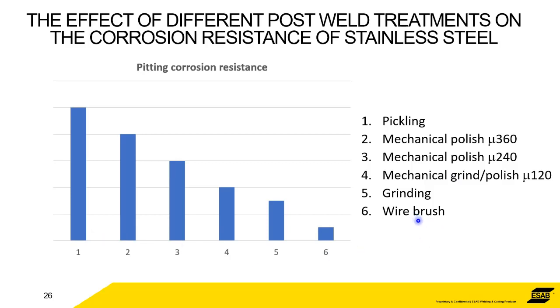Number 6, we've got the wire brush. So it doesn't really matter what the numbers are. We're just trying to illustrate that pickling is 10 times better than using a wire brush. Grinding is 3 or 4 times better than a wire brush, because you're sure to get rid of both the heat affected zone, the heat tint, and the chrome depleted zone underneath. You're sure to get rid of that by grinding.